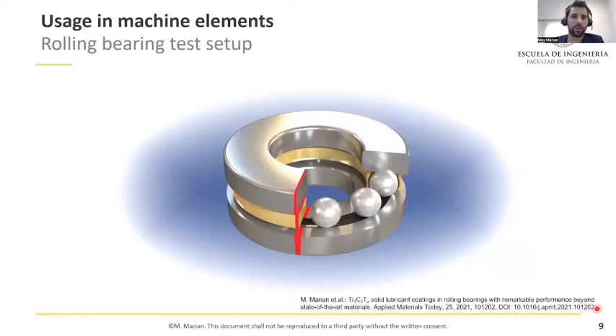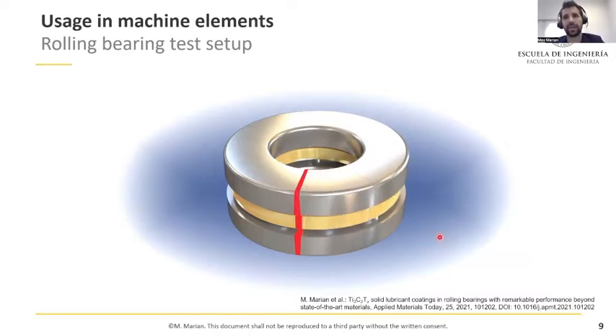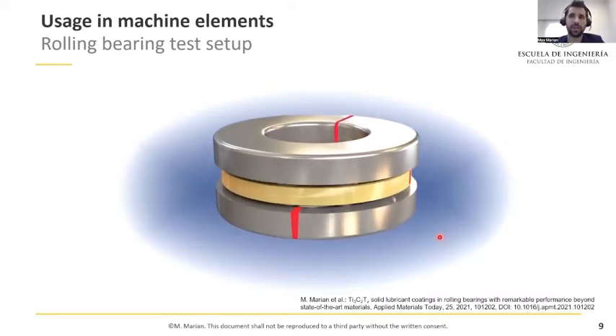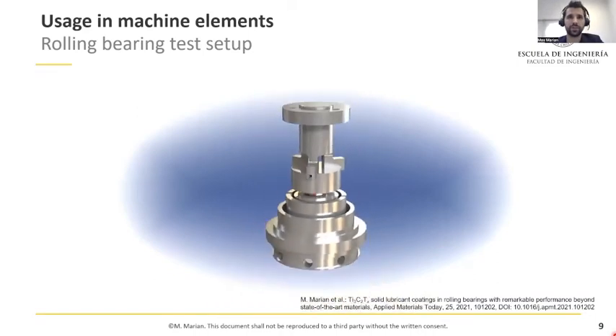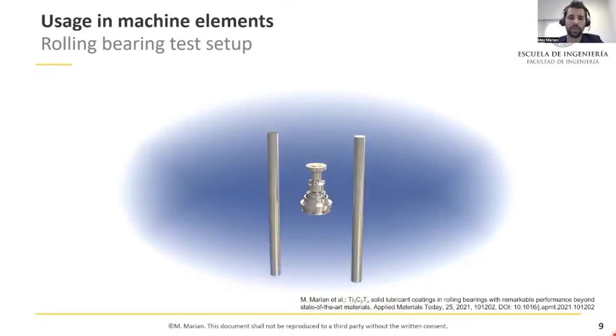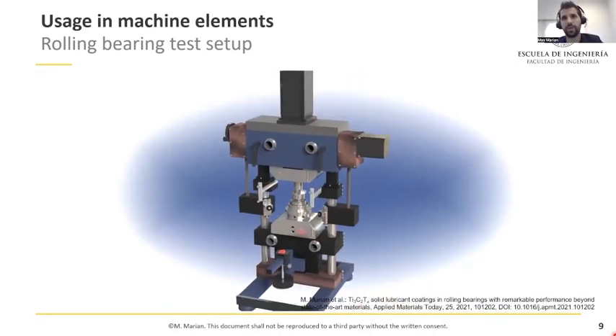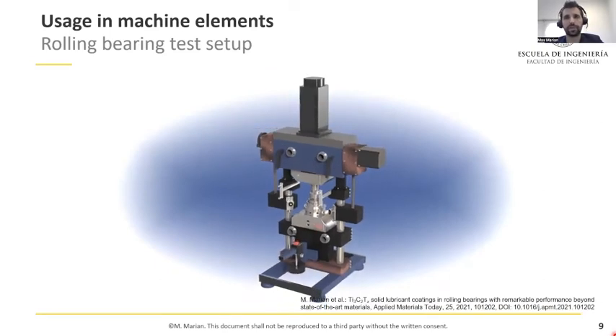So what we did were some tribological measurements on the component level using this kind of thrust ball bearings. The bearing consisted of balls, a sheet metal cage, and two bearing washers. The upper washer was driven while the lower washer was stationary, and the ball system was mounted into a Wazau tribometer operated under atmospheric conditions. The upper washer was driven with an electric motor at 1000 RPM, and we applied a load of 130 Newton.